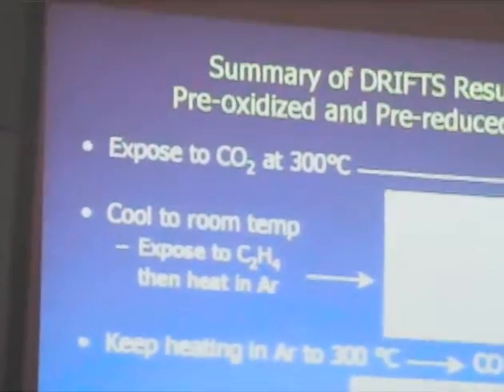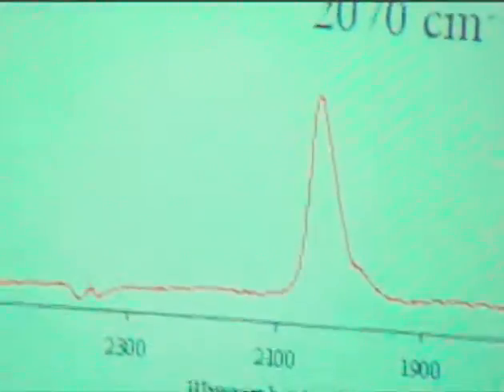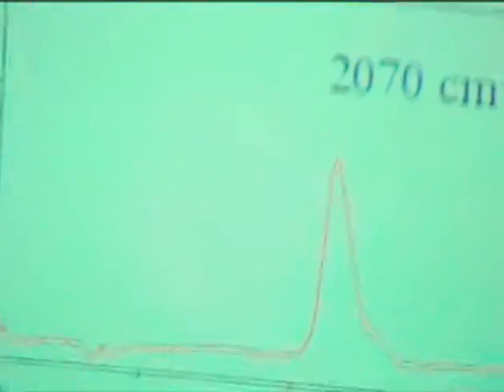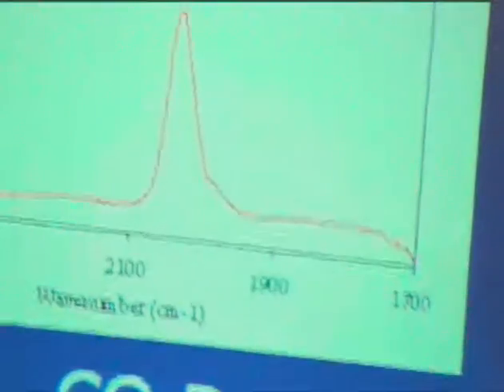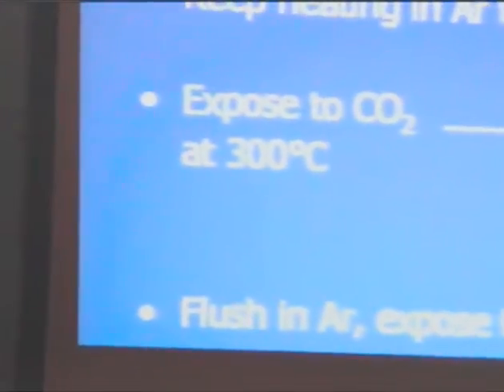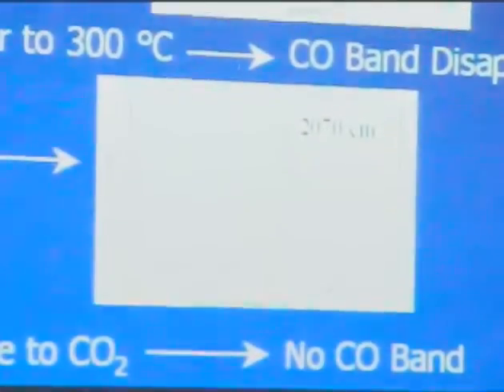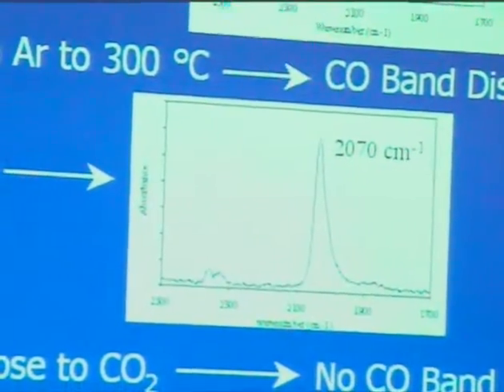So we wanted to probe why that CO2 dissociation was stopping, what was happening with that mechanism. We did some DRIFTS studies on pre-oxidized and pre-reduced platinum zirconium material. We oxidized these materials at 300 degrees C and then did a low temperature reduction so that we would only reduce the metal and not reduce any of the support material. After that pre-oxidation and pre-reduction, we exposed it to carbon dioxide at 300, and we saw no CO band on the metal, so no linearly adsorbed CO.